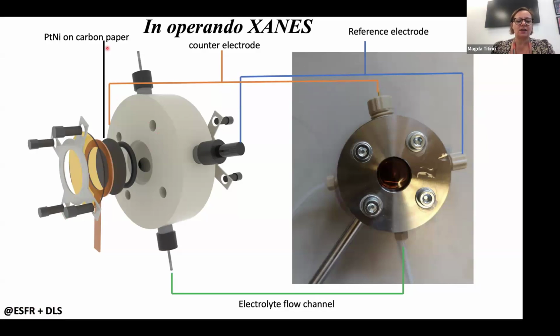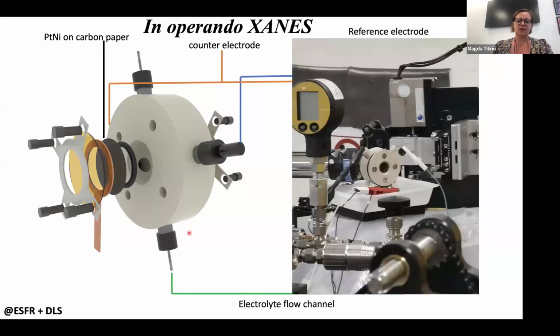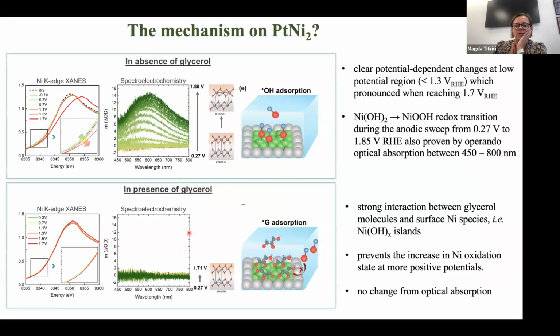So we have here our working electrode. We have our reference electrode here on this side. And then here we have our counter electrode on this side. And here we are flowing the electrolyte. This is how this cell looks when it's mounted in operando. And then what we collect is this XAS spectra, where you're looking at the nickel K-edge.